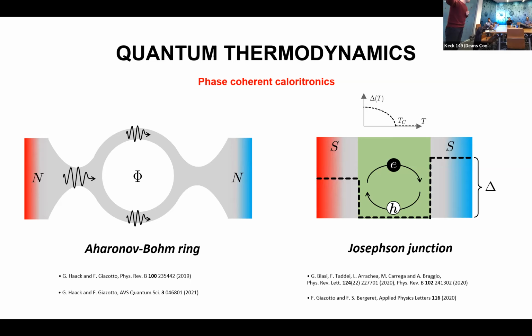And the second and very important characteristic of superconductors is that they are characterized by an energy gap delta, which depends on temperature. More specifically, this energy gap, which is just the gap between the Cooper pair condensate and the quasi-particle spectrum, is maximal for very small temperature, and then it closes when it passes through the critical temperature.